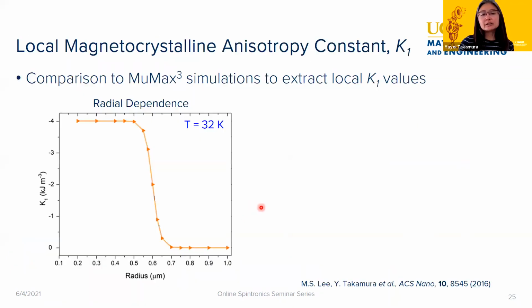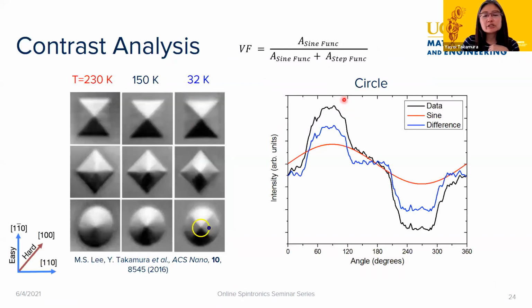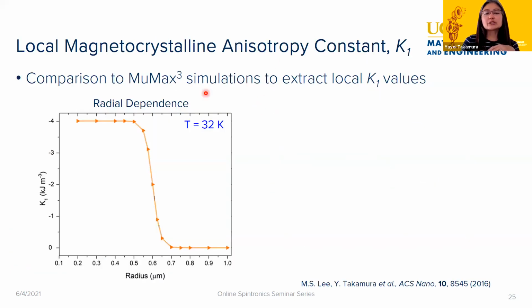And what he did then is that he went into MuMax3, right? And then actually did some simulations in order to get MuMax to match up with basically the same type of P images and this vortex fraction. So he was using this vortex fraction as sort of his parameter to compare our experimental data to the MuMax3 simulations. And then what he found is that the only way to match things up was actually to have a very sharp radial dependence of the magnetocrystalline anisotropy, right?